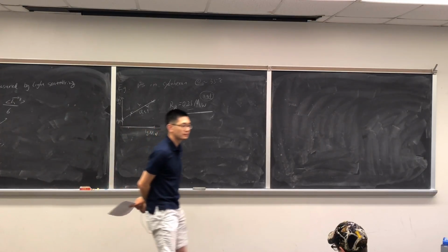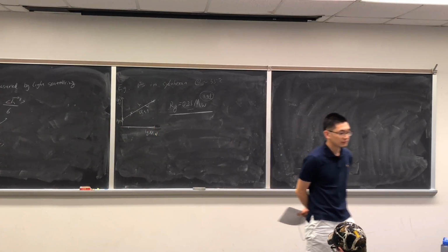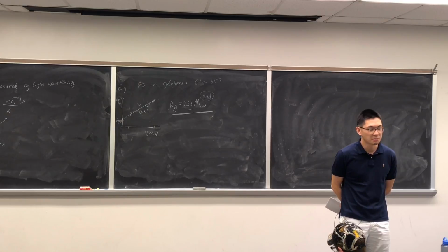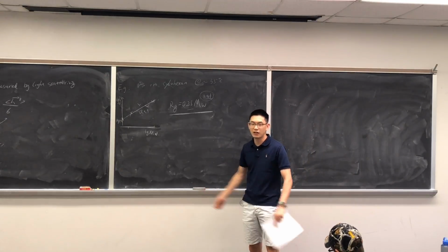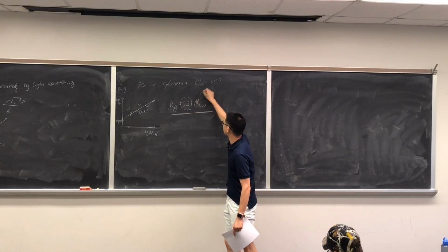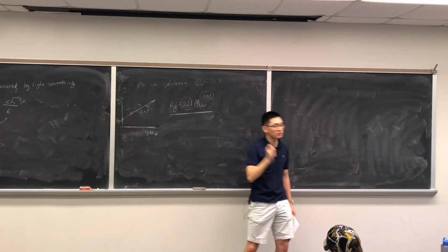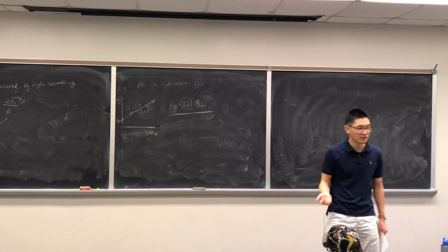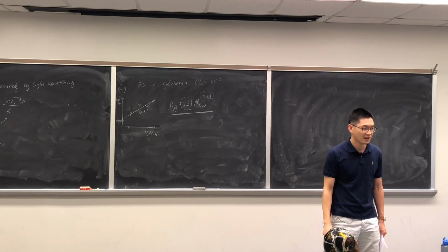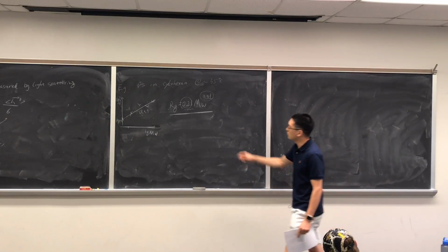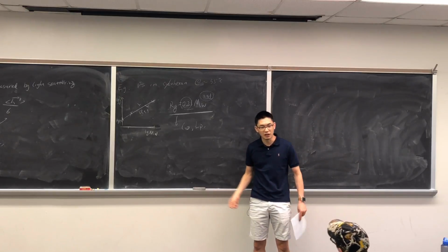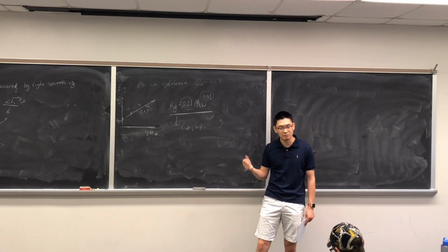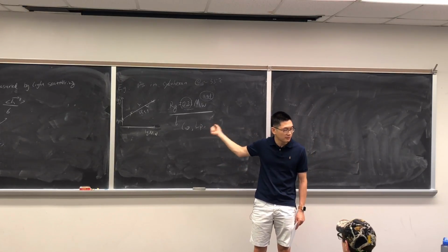Question? Is the 0.25 specific to cyclohexane, or is it true for all polymers? Oh, it will depend on the material. This is just generalized for all the different polymers. You will get different exponents and different prefactors. It is material dependent and solvent dependent and even temperature dependent. So what we can do is use this to understand what these parameters are, and you can know how rigid your chain is in this particular case. Okay?